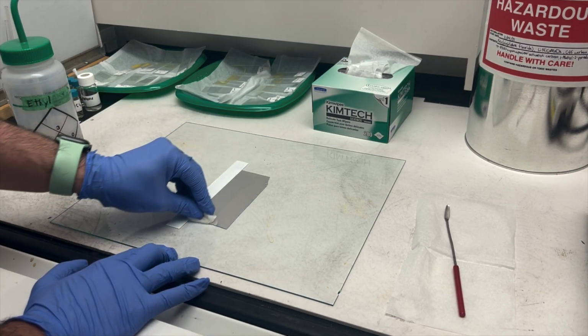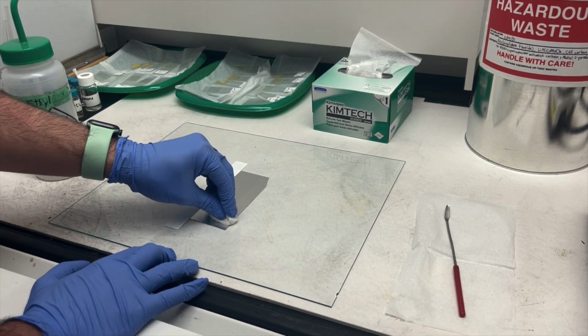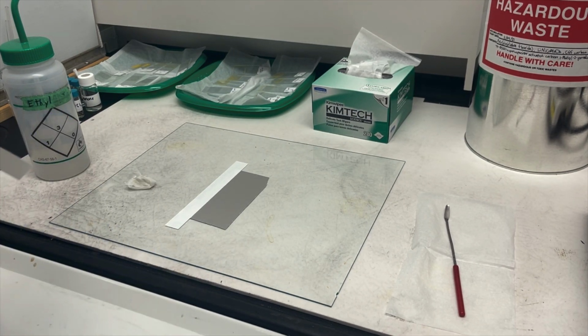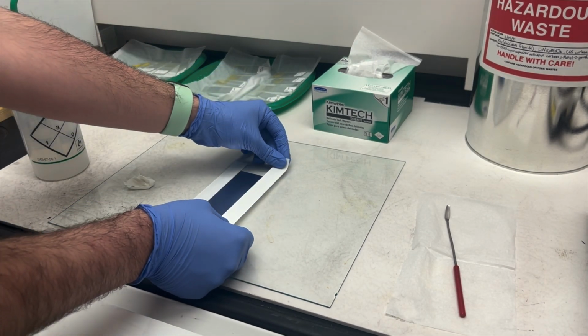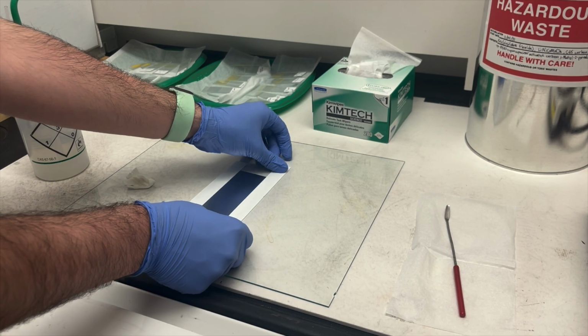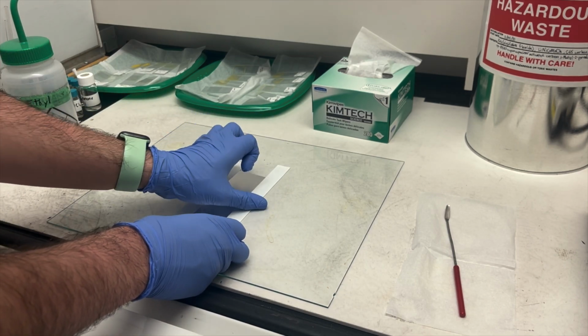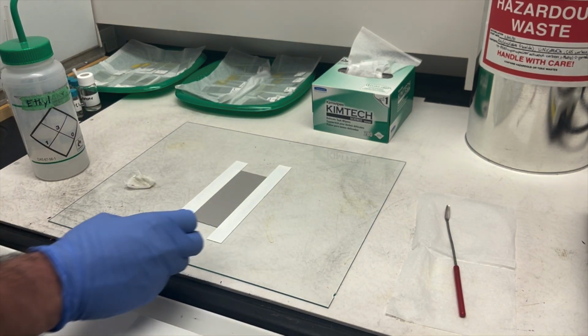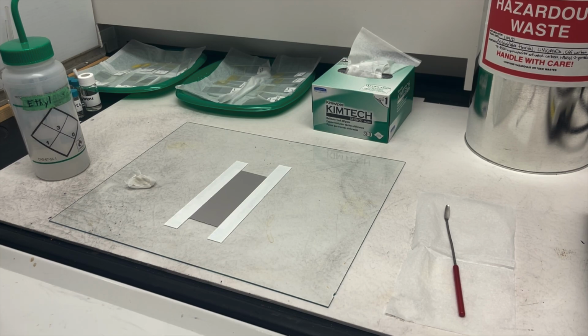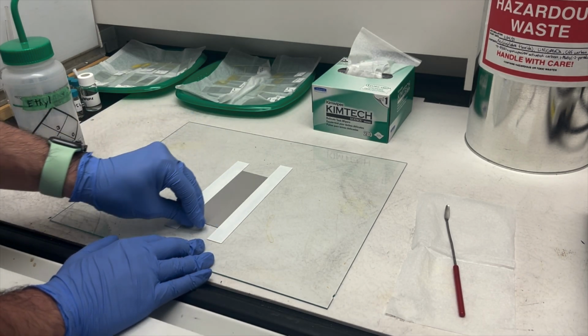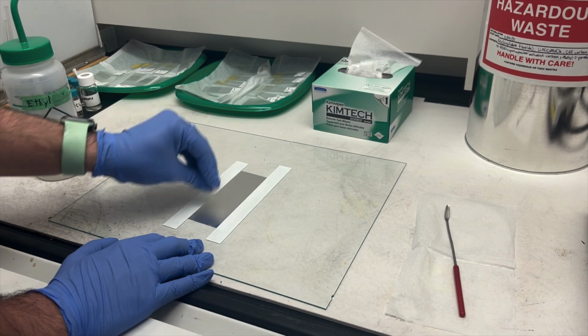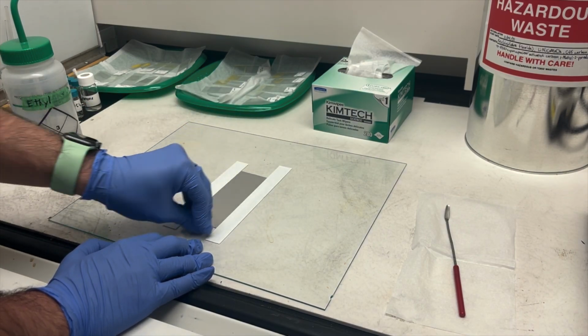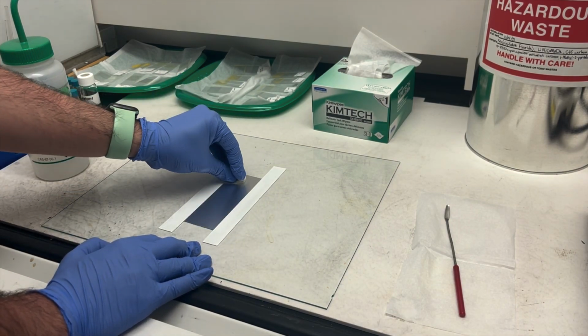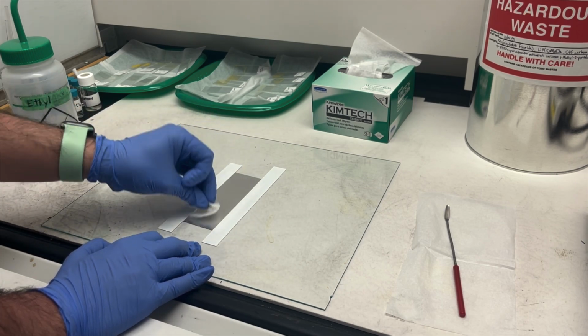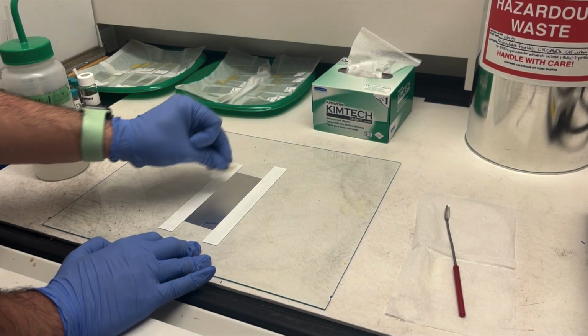The thickness of the deposited slurry can be varied by adding more layers of tape. Ideally, the tape should be longer than the strip on either side. The size of the strip should depend on the amount of slurry made. More recipes should either be longer, wider, or perhaps both. The size of the strip for single recipes should be long, but relatively thinner.